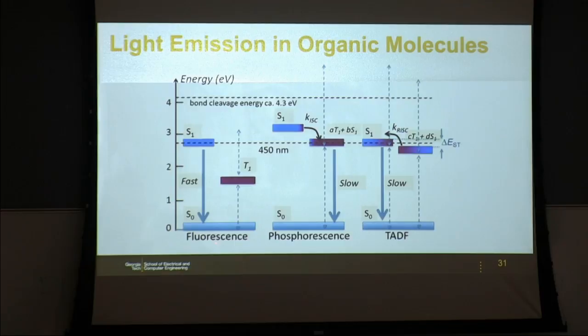And then came along phosphorescent materials. Phosphorescence as a process has been known for a long time. There, you can design the molecules by adding a heavy element such that you have spin orbit coupling, which mixes the singlet and the triplet states. Because that triplet state now has a little bit of a singlet component, you can have light emission. It's just much slower because the electronic coupling is weaker. Okay, but you can have efficient intersystem crossing, and so you can harvest 100% of the light here. Another way, and this is the latest, is very exciting because this one works very well for green and red emitters, but there's a problem for blue emitters.